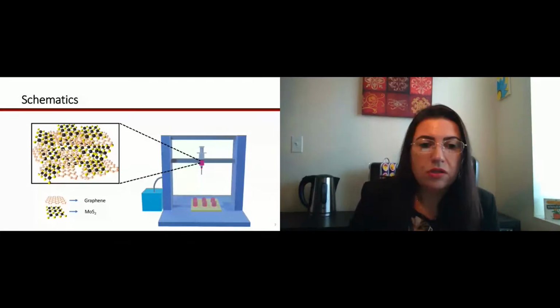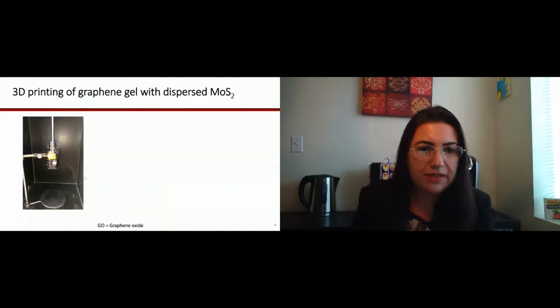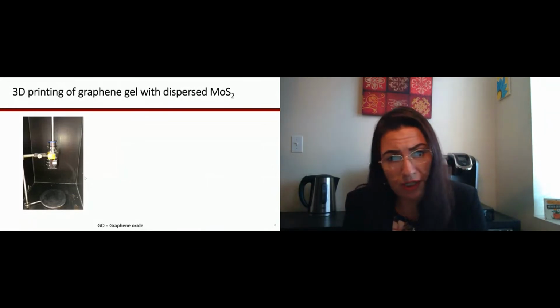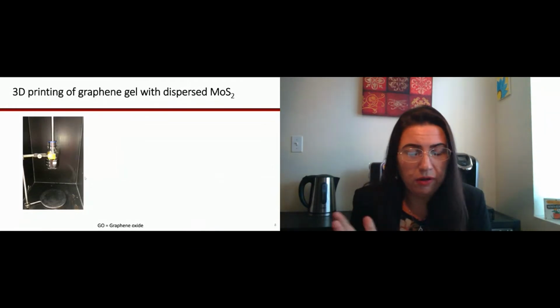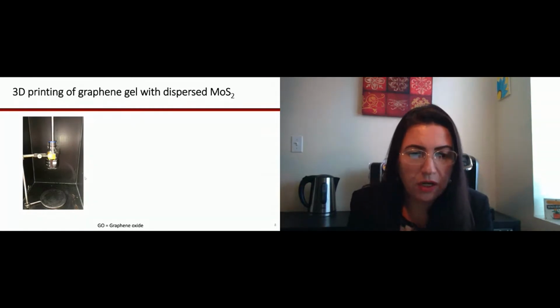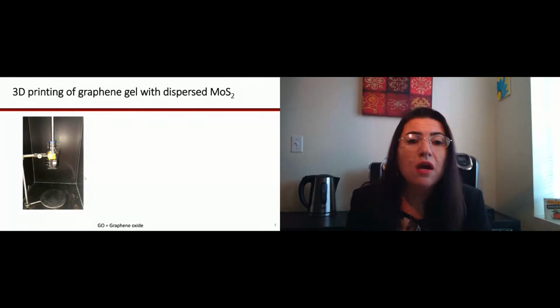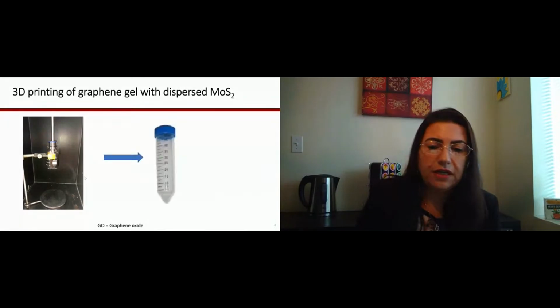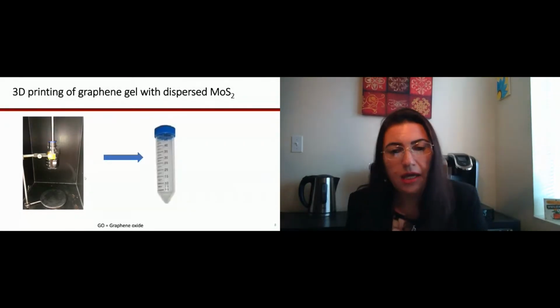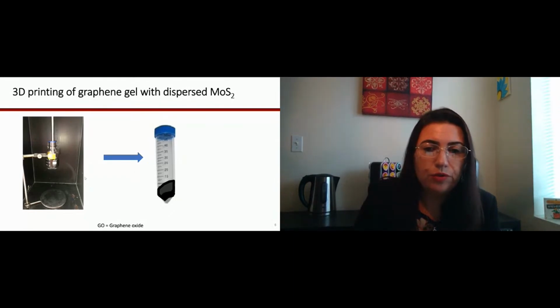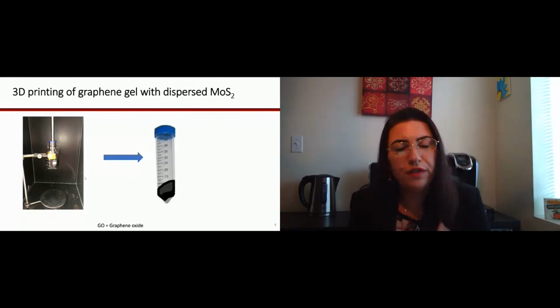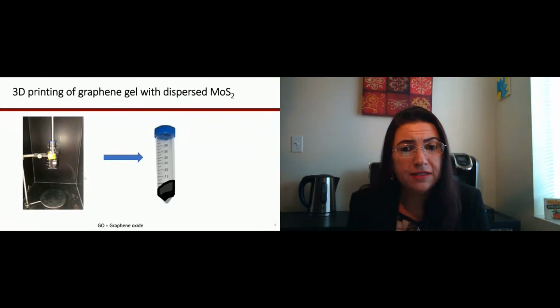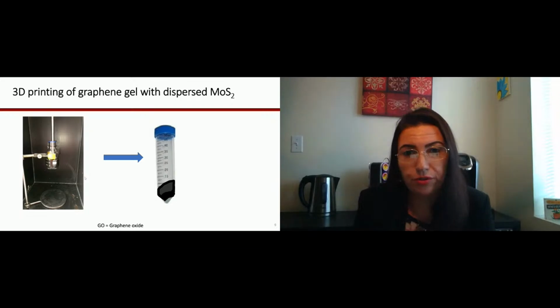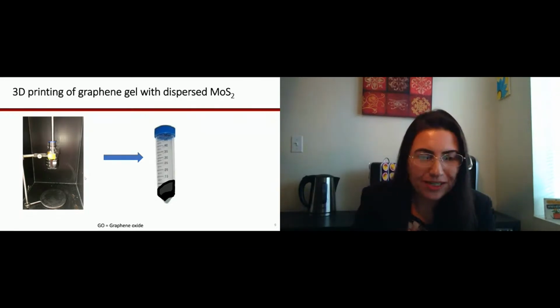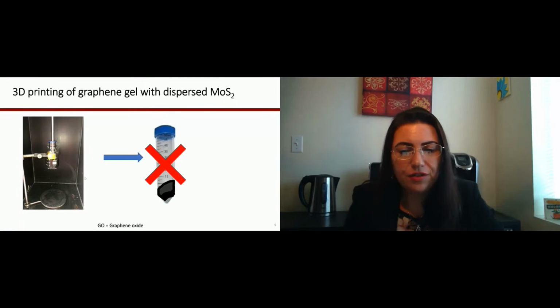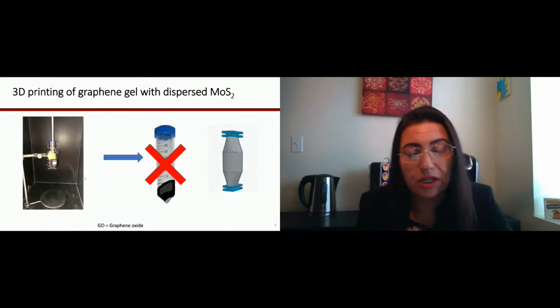So the first part of the process was mixing graphene and MoS2. We used a tip sonicator that's been used a lot already with many different materials. But the interesting thing is that what a lot of people do, especially for graphene gel, is supercentrifugation. Once we used graphene and MoS2, with the difference of density, we had phase separation, and that meant we couldn't use supercentrifugation anymore. So we had to find a different way to concentrate the solution and create the gel.